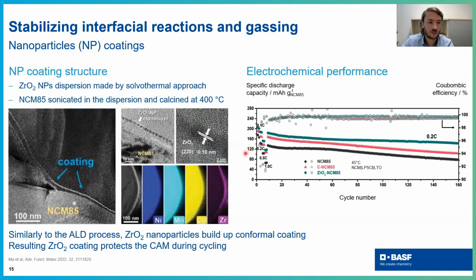There are other techniques, like you can also use nanoparticles. This is a very nice method developed by Yuan Ma here at BASF, and he has prepared a zirconium oxide nanoparticle suspension and immersed the cathode material into it. And then you can see in TEM a very nice layer formed out of these small nanoparticles. And this layer seems to be quite homogeneous, as shown here in EDX mapping. And you see immediately improvements in the cycling behavior. Actually, a very similar effect as we just saw for the ALD coating.